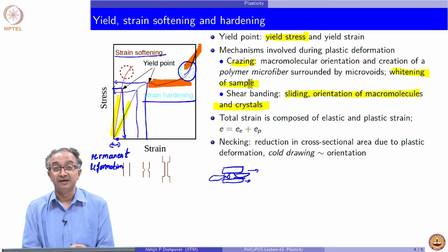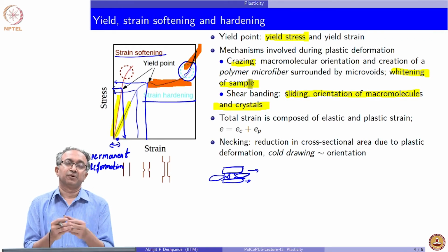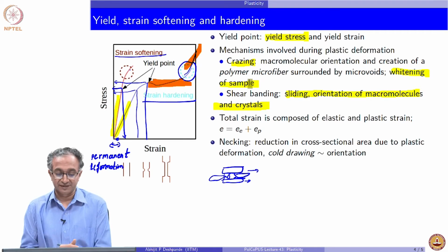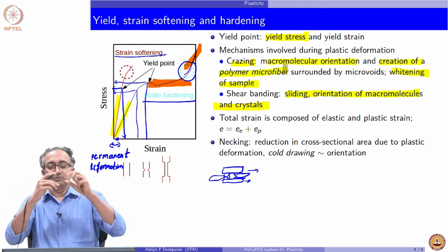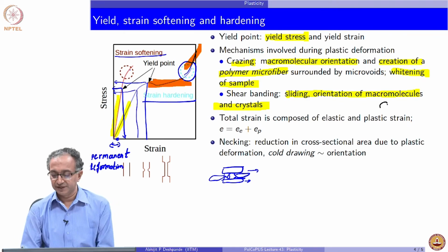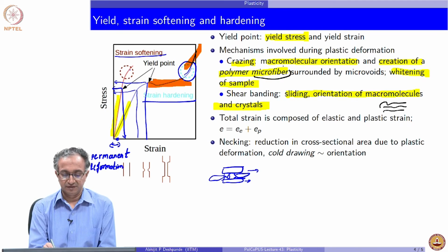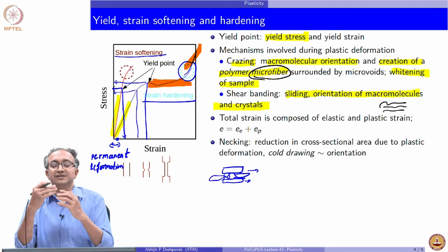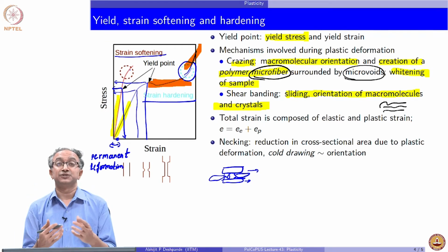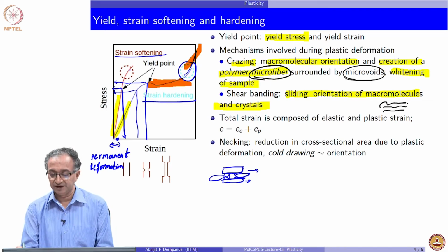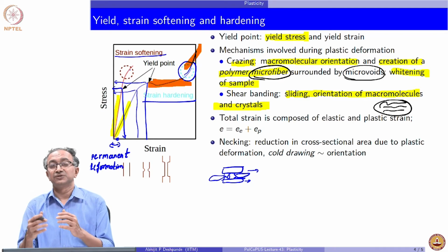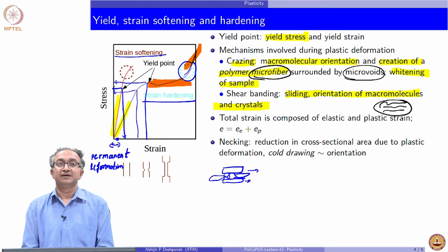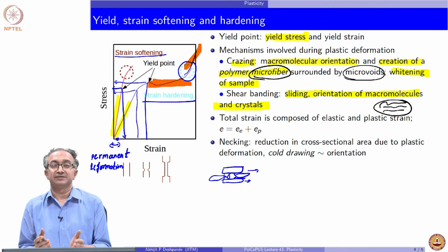Crazing actually leads to whitening of a sample, and I am sure a lot of you have seen this: if you take some polymer films and stretch them, they start becoming white. What that is due to is that the macromolecules start orienting themselves towards each other, and they form a fibril. Because the chains are coming together and getting oriented, there are microvoids between the microfibers, and that is what leads to whitening. Whenever you have these density fluctuations, so we have a region of polymer and then a gap and then another fiber, light scattering takes place and the material becomes white. So, both crystal sliding and chain orientation are important during plastic deformation as well as crazing, depending on the polymer.